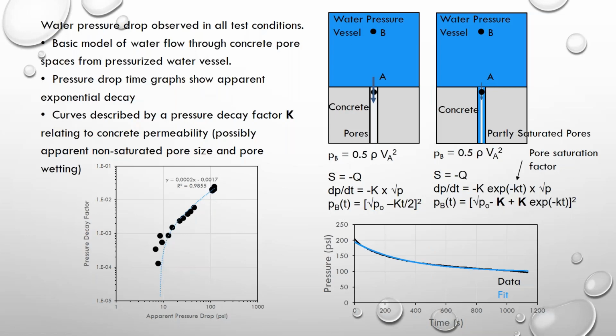So we try to model this in terms of a mass balance and energy balance system. So the first case considered is when we have a pressure vessel, the water held at 200 psi, for example, and we first assume that the concrete pores have low pressure and the water can freely flow through these pore systems, an apparent pore system. When we solve this problem, again, with mass balance and energy balance, we get an equation, but unfortunately the fit wasn't great. And so the curves that we see, the decay actually is a factor of time. So it seems like the pore sizes are changing with time, which makes sense because the pores are essentially getting saturated with water with time.